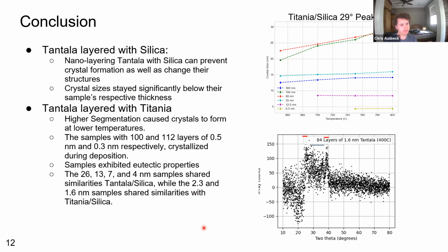And then with tantala layered with titania, we saw that higher segmentation caused crystals to form at lower temperatures. And specifically, the samples with 100 layers and 112 layers of 0.5 nanometers and 0.3 nanometers respectively crystallized during deposition. So these samples were so prone to crystallization that they crystallized during deposition. And we believe this is because of the mobility of the molecules during this period.